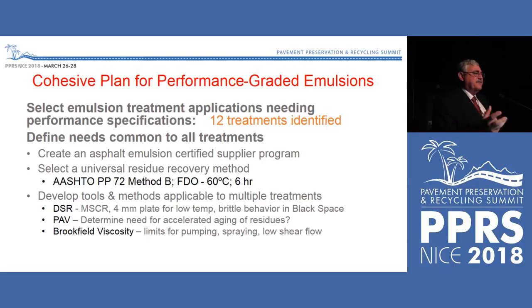For hot mix, it's about this surface cracking, and we're using parameters like the Glover-Rowe parameter and delta TC and things that are now showing up in the literature for cracking, but also for brittle behavior and aggregate loss at low temperatures. Same sort of thing. We can define that brittle behavior with the DSR. We don't need a frost test or some of the other tests we've traditionally used. For PAV, we're trying to decide if we need PAV aging for emulsion residues.